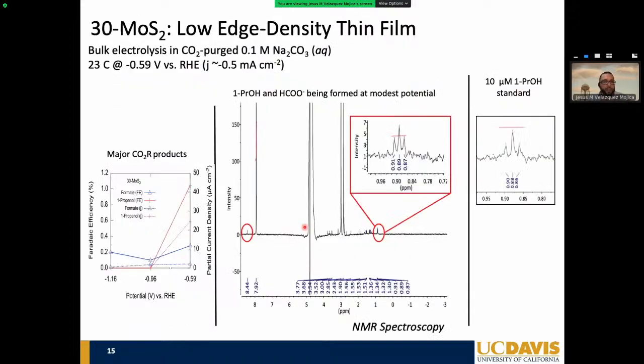So what do we see? Well, at 23 degrees Celsius and an applied potential of about 600 millivolts versus RHE, we see something really surprising. And it's actually this triplet here. And that is exactly the location where protons from propanol are distinctively present in the NMR.